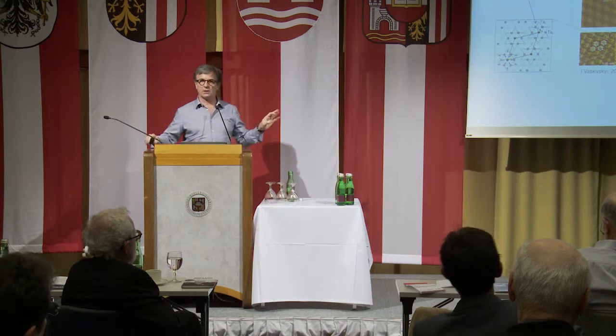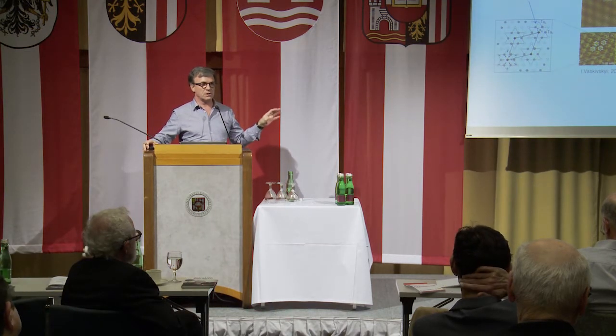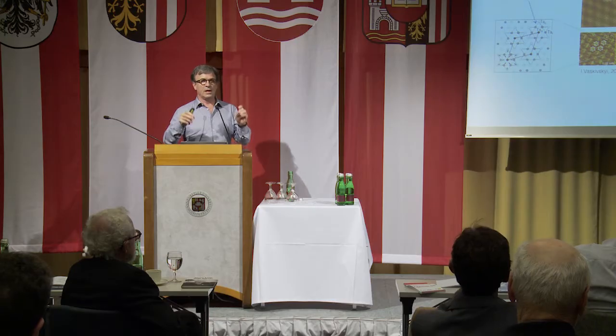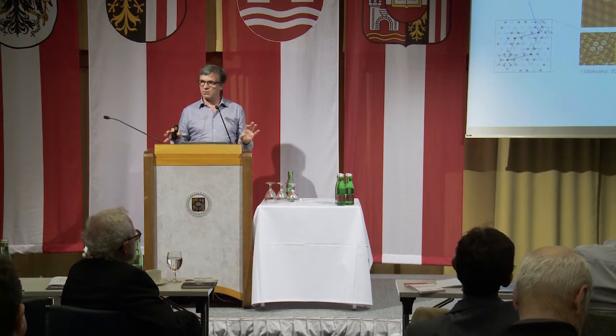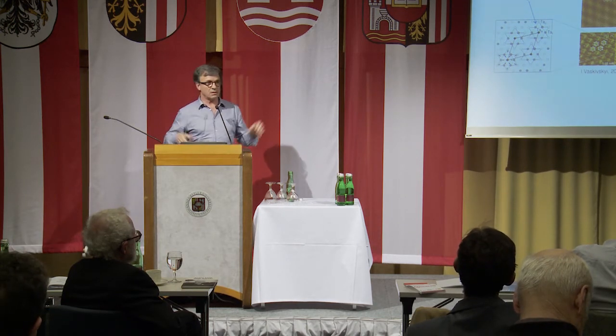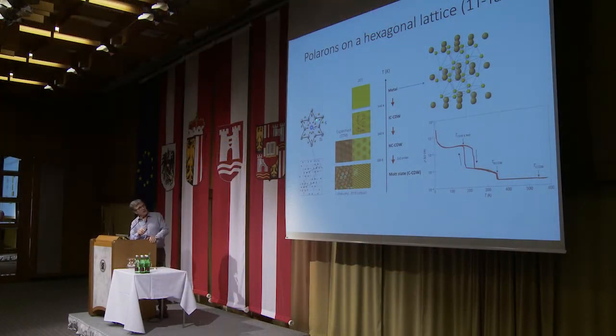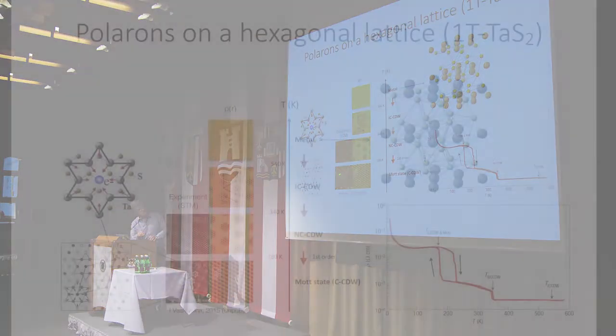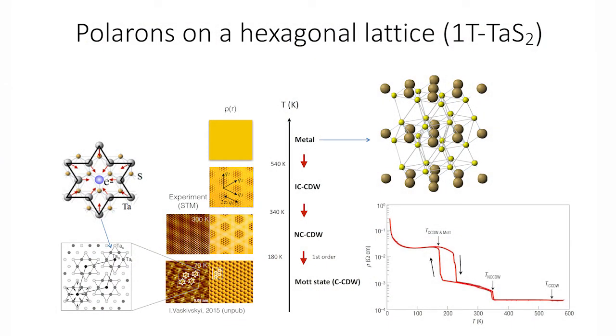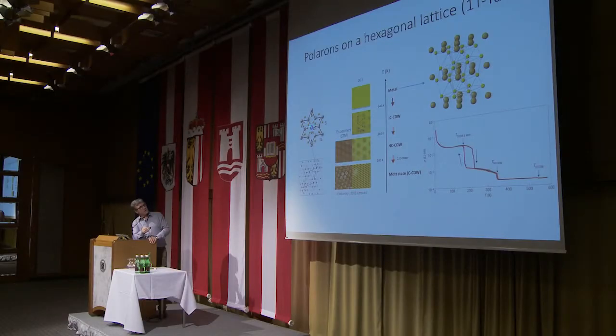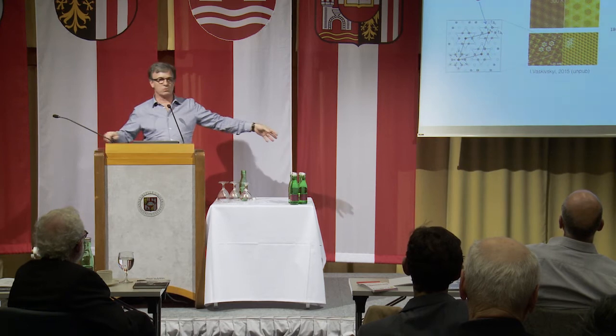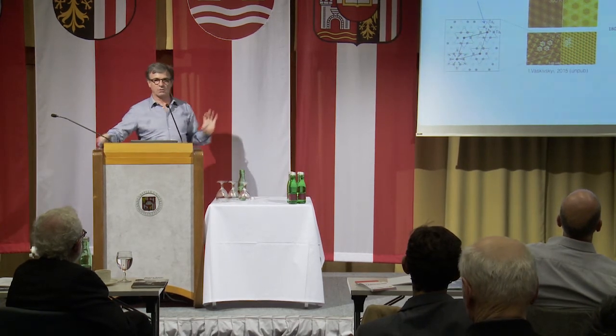Now, the good thing about these materials is that because these polarons are ordered, you can tell the position of every atom, the charge on every atom. You basically know everything about this polaron, the displacements and the charge, okay? And in fact, they look like this. This is an STM picture, by the way. You can see these hexagons. This is the Star of David, in which 12 tantalum atoms are displaced towards the central tantalum atom, okay? And this forms one polaron. That's a fact, experimentally measured by X-rays, electron diffraction, anything you want.